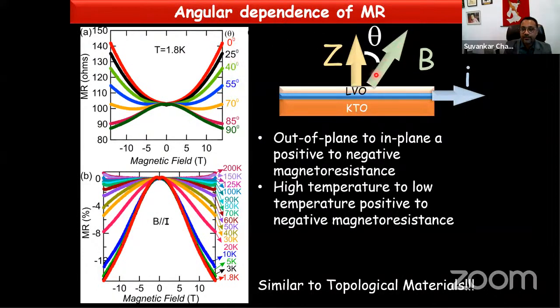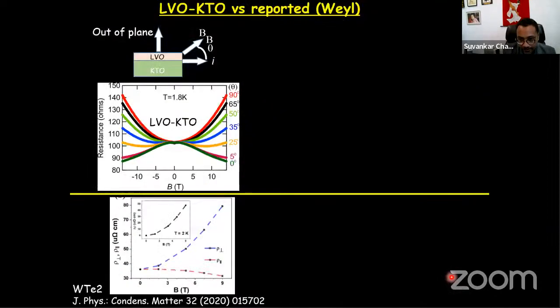that is, the magnetic field is along the Z direction, it gives a positive magnetoresistance. But when theta equals 90, that is B parallel to the current, you see a negative magnetoresistance. And this negative magnetoresistance becomes positive magnetoresistance with increasing temperature. This is very similar to what people have seen in topological materials.